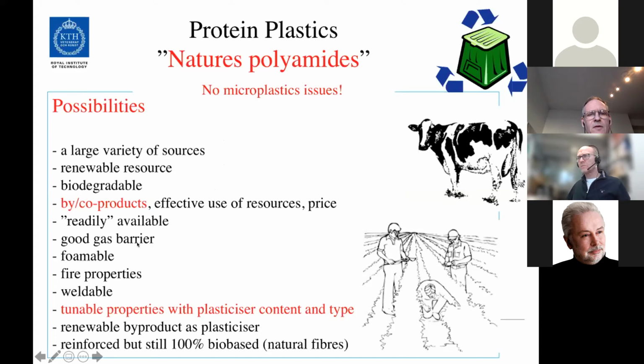It's a renewable resource, it's biodegradable, and you can use by- and co-products, which leads to an efficient use of resources. It is readily available, depending a bit on what the actual material is. Proteins have a lot of hydroxyl groups, so they form strong networks, and that's the basis for achieving a good gas barrier. So they are usually good gas barriers. Foamable, they have quite good fire resistant properties, which I will show. And you can tune the properties by using different contents of plasticizer.